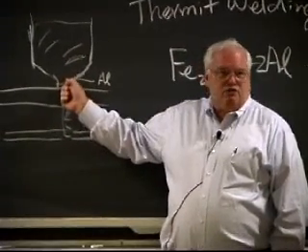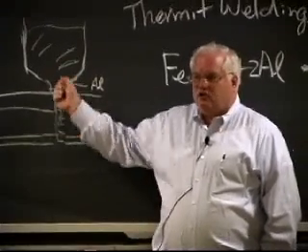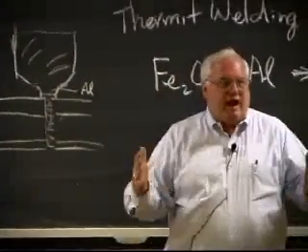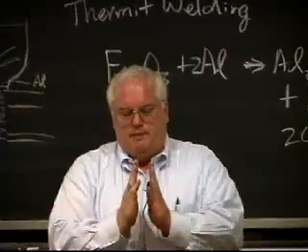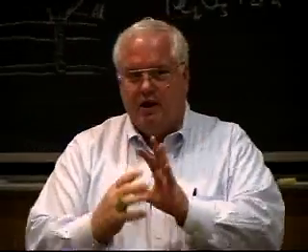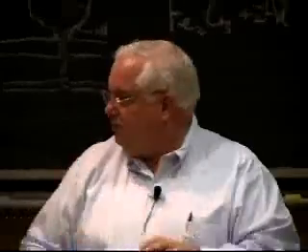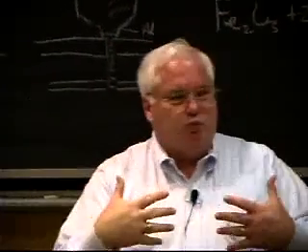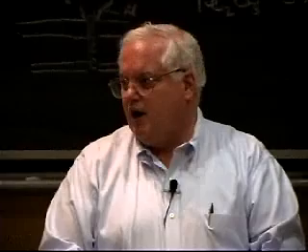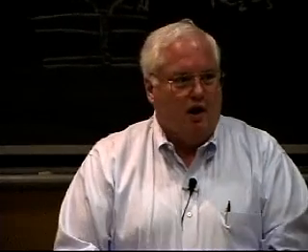It obviously just melts through this little disc that's kept the sand from dropping down here. So the molten iron now falls in here, and you make a little casting. Originally, your rails were about 1 inch apart, and you put these little sand molds, which have the shape of the rail head. They're already pre-molded. Just clamp those up against the side, put the bucket on top, pour the sand in, start it with a blasting cap, stand about 30 feet away, because this does generate some sparks and stuff too. And all of a sudden the molten iron basically just drops right in there. No power requirements, you know, it's nice and flexible.